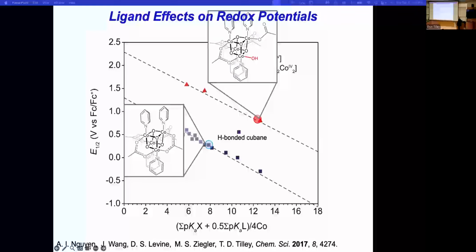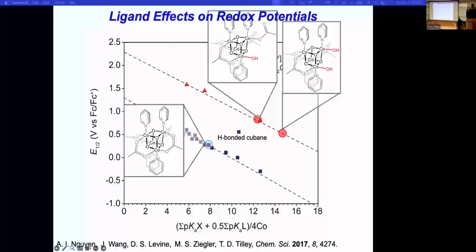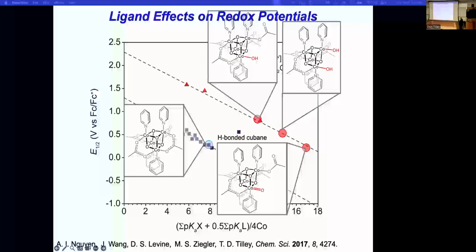And if we think about this hydroxide species and a disproportionation between those two species, what we see is that this species is really a little too high in energy to do that. So we ruled that out as the partner for that redox disproportionation. You could fully dissociate the acetate. Now, these potentials are really easy to calculate, right, from using this relationship. And this is really not that close either. But if you form the oxo, it's right in the vicinity for that disproportionation to occur and be energetically favorable. That's why we think the deprotonation happens first.